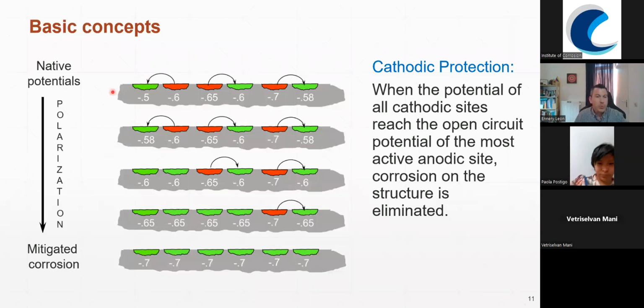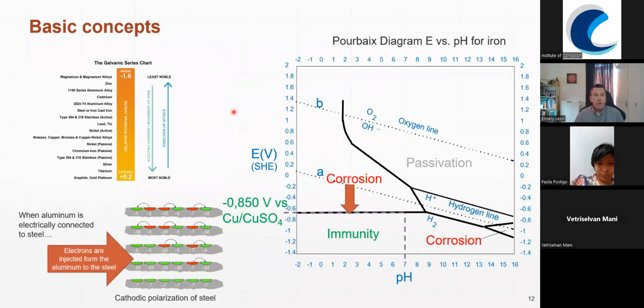Usually when we have a piece of steel in the soil, we might have a natural potential of minus 500 millivolts versus copper sulfate electrode, and then we want to polarize it up to minus 700, or later on in the next slide, we will see that minus 850 millivolts is the good target. So what do we do with cathodic protection? Basically, when we use, for example, aluminum anodes connected to a steel structure, as you can see here, aluminum is more electronegative, more active than steel. So it will tend to provide electrons to the steel, and then the polarization of the steel will take place, and we will do this.